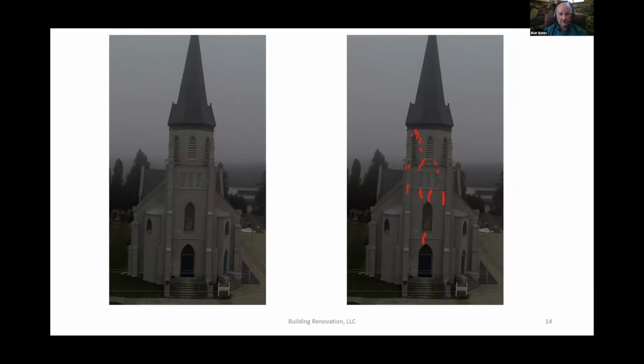This is a building south of Grand Rapids, built in 1904. And we were called in because they had all of these cracks and they wanted us to seal the cracks and repaint the building. And cause and effect of, no, the cracks are on the right-hand side here. So we flew a drone, photographed everything, and then mapped everything. And so these cracks are a pattern that tells us that something's going wrong here. There's steel inside of the steeple, right below those louvers, and the steel is corroding.